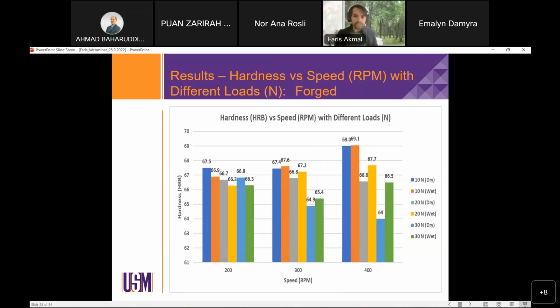Now, the result for forged cases in hardness value shows that for 200 rpm, for each load, the lowest is 66.3 for 20 Newton wet and 20 Newton dry. The highest is 67.5. For 300 rpm the lowest is 64.9 and the highest is 67.6. But for 400 rpm, the lowest is 64, but the highest is almost similar, which is 69 or 69.1 for 10 Newton dry and wet. If you compare forged and unforged, the hardness for forged is higher than the unforged.